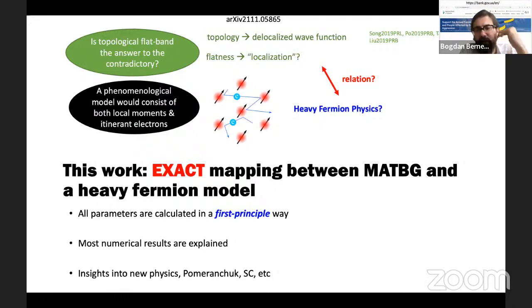And this model basically gives you a separation of scales of which electrons are responsible for the interactions, for the large interaction physics that's observed in this system, and which electrons are responsible for the itineracy and topology of this system. And a lot of the results that were obtained in Hartree-Fock or strong coupling pictures can now be understood in a very simple, intuitive way. And you can have new insights into the superconducting gap and transition temperature, although I don't claim that is yet a solved problem even in this formalism, because it's still a very hard model to solve.